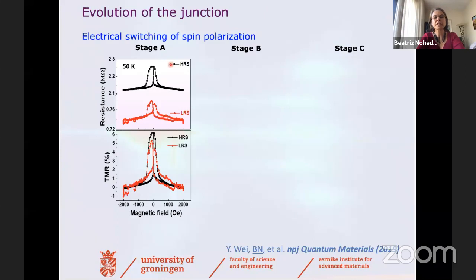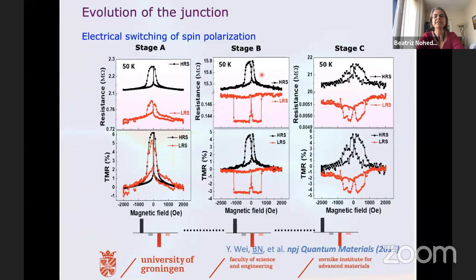But then if you keep on cycling, you go into a completely different behavior. And at some point, after enough electric field cycling with the same voltage, you can see that you have a huge effect in the TMR. You have a reversal of the TMR effect. So we were worried that we didn't have a magnetoelectric coupling, but we actually have a huge coupling after cycling. And this becomes weaker, but still present when we further cycle the samples to stage C.